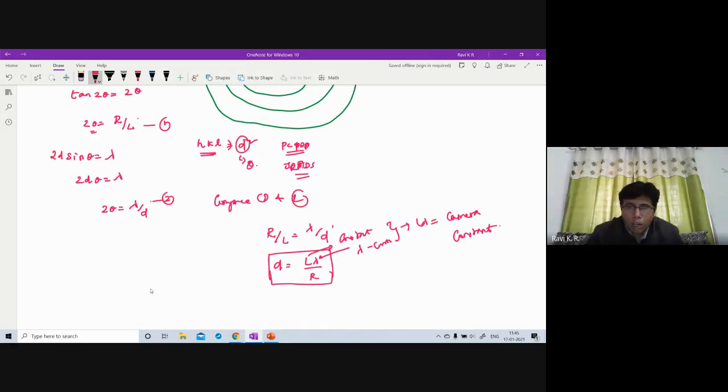This is the one that you can calculate when I run a calibration file. Let's say I'm operating this machine at 80 kV, then you have to calibrate it for running the machine at 80 kV, 120 kV, 200 kV. You do that, then automatically you get a camera constant for this particular sample.